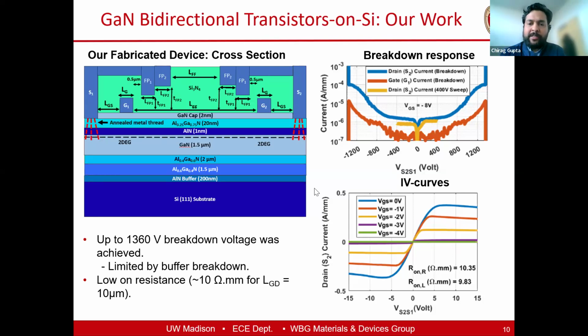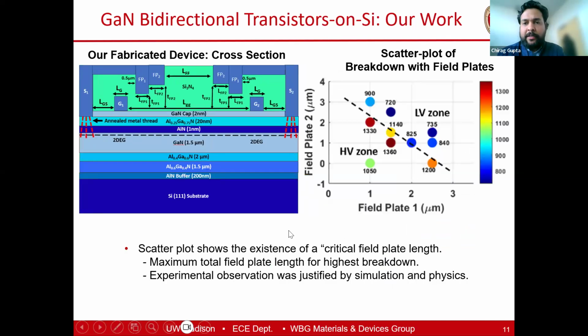And of course, these breakdown numbers were obtained with optimization. It wasn't as trivial. One of the things that we noticed, and we tried to see what helps in achieving this breakdown for 10 micron of gate to gate spacing, was that there was a particular field plate design that helps.